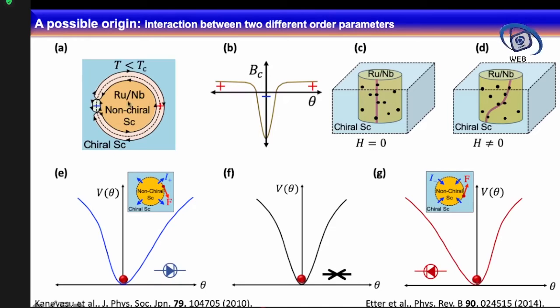If we combine all these results, we can explain it in the following way. We have a ruthenium inclusion in our strontium-2 ruthenium-4 superconductor, which is embedded there. So we can establish that the situation is this: we have a normal superconductor surrounded by an unconventional superconductor. It means that the order parameters of these two superconductors are different and non-compatible, so some kind of frustration will develop.